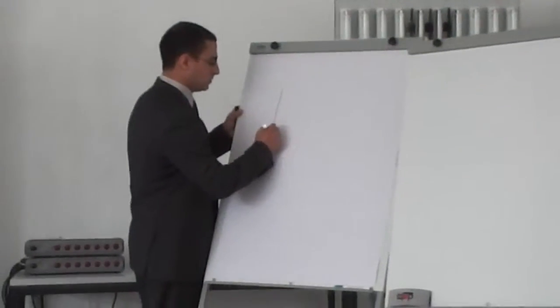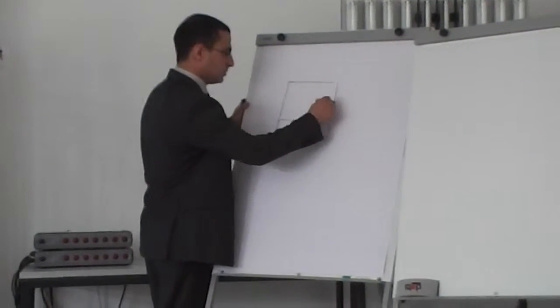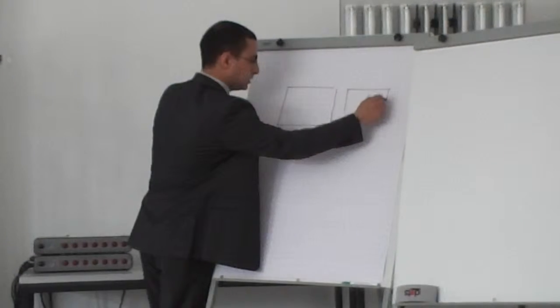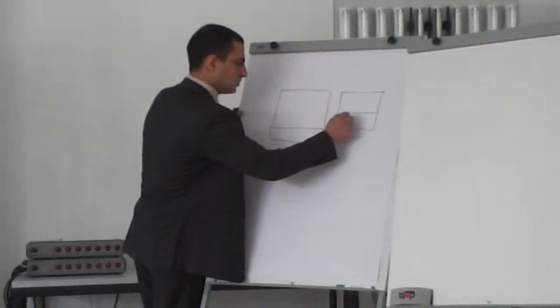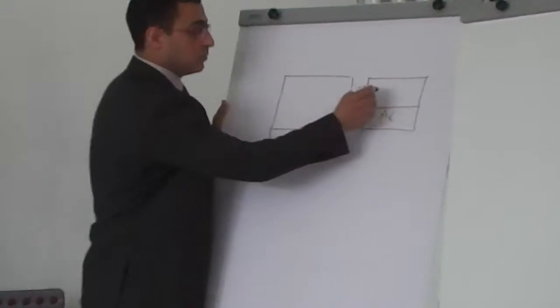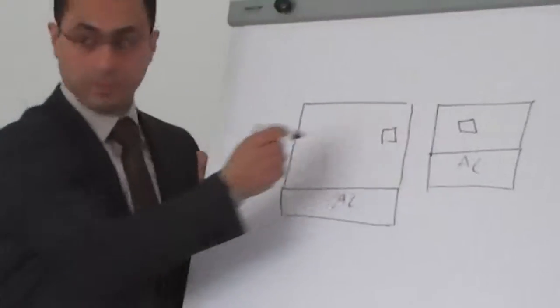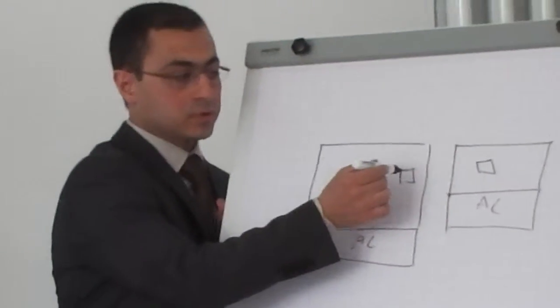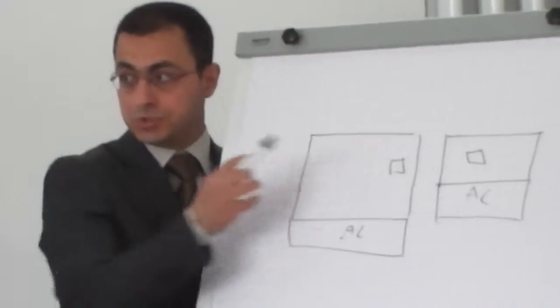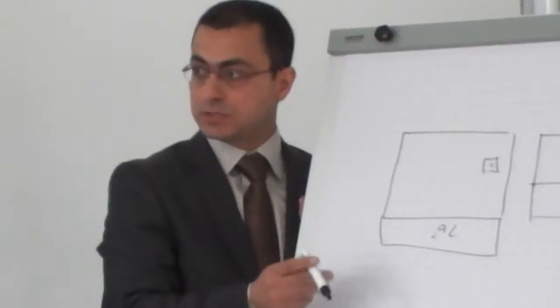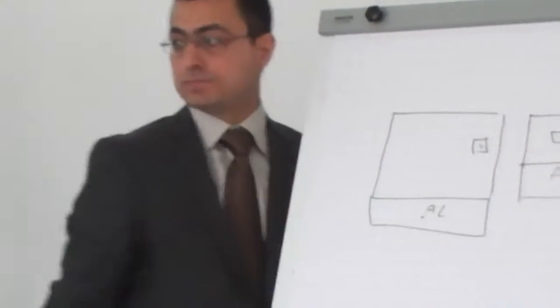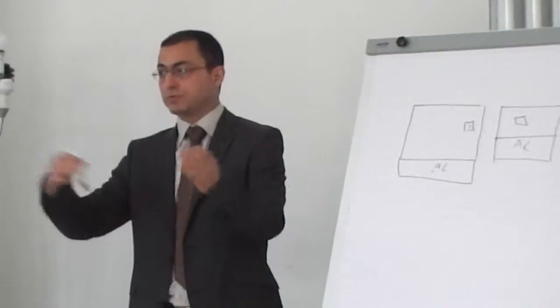Yes. Why nano? And what really is the effect of that? I'd like to explain something. This is the film without nanoparticles here. When I take the same size from 2 films, this one has nanoparticles. Shrinkage here is more than here, because in this area I have nanoparticles, which take part of this volume. So shrinkage here will be less than here. Change in the dimension will be less, and therefore cracks will be less.